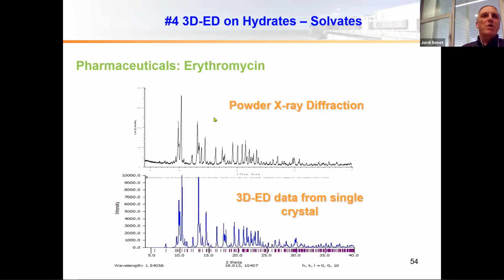But anyway, if we simulated from the structure the powder diffraction pattern of this phase, it corresponded exactly to the one we expected to be the dihydrate. So again, in a quite easy, quick experiment in a morning, without doing any crystallization. In fact, I was breaking the crystals to get them smaller. We could get an answer to our question and the structure solved of the dihydrate.